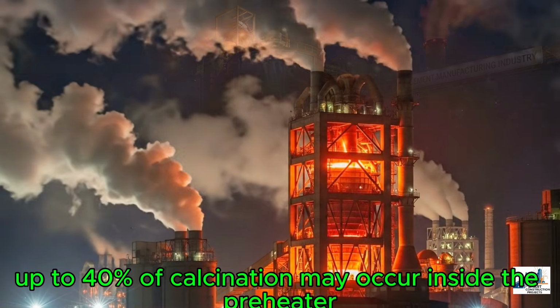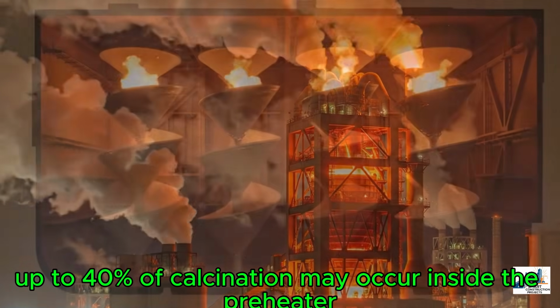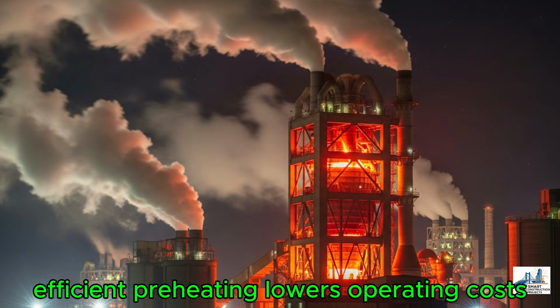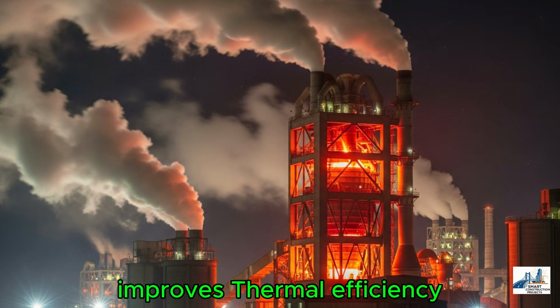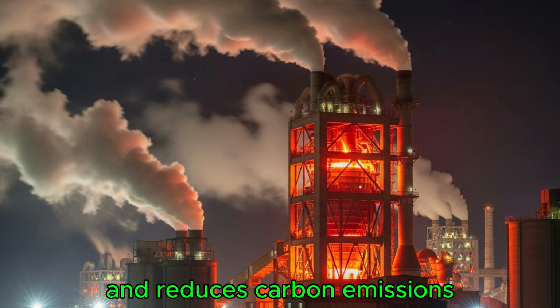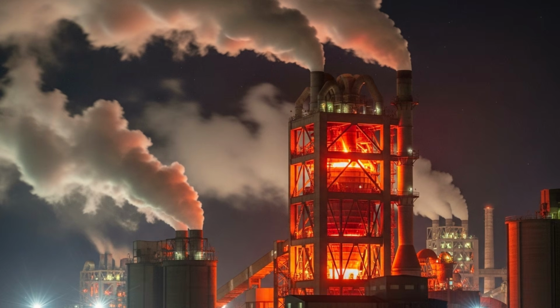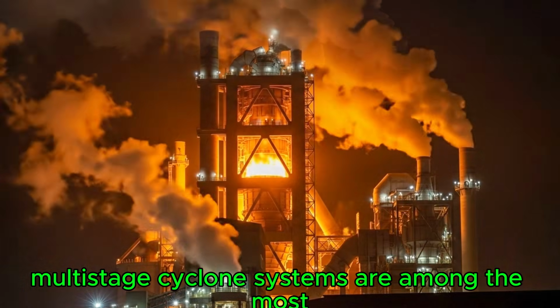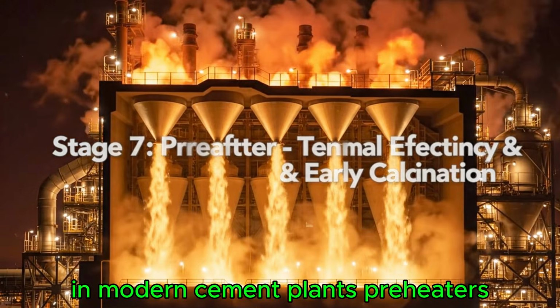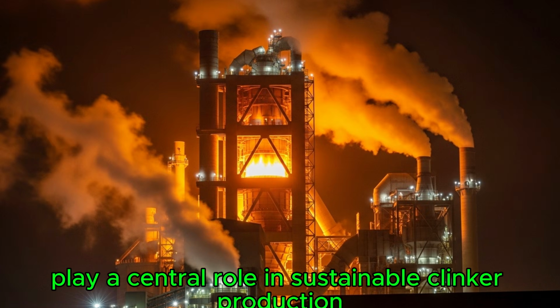Up to 40% of calcination may occur inside the preheater, significantly reducing kiln fuel demand. Efficient preheating lowers operating costs, improves thermal efficiency, and reduces carbon emissions. Multi-stage cyclone systems are among the most important energy-saving technologies in modern cement plants. Preheaters therefore play a central role in sustainable clinker production.